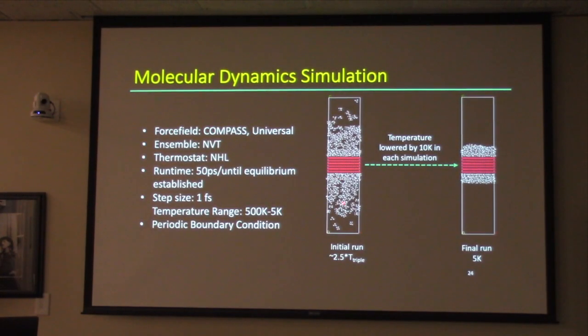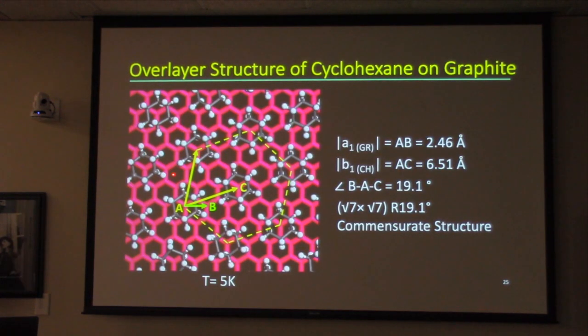So one of the other things that we do is we study what happens when we increase the number of molecules in the cell. The details aren't as important as the fact that molecular dynamics simulations basically follow Newton's laws of motion. So you start off with a particular temperature and some particular velocity, you know what the energy is because it's basically just k Boltzmann times the temperature, and then you follow the trajectories for some certain amount of time. We're really lucky because we have 1 femtosecond step sizes, and we really can run them forever. Typically, these runs on fast machines are on the order of 3 or 4 hours apiece, and it's really not so bad. What we can find is things like what the individual structures are of these particular systems.